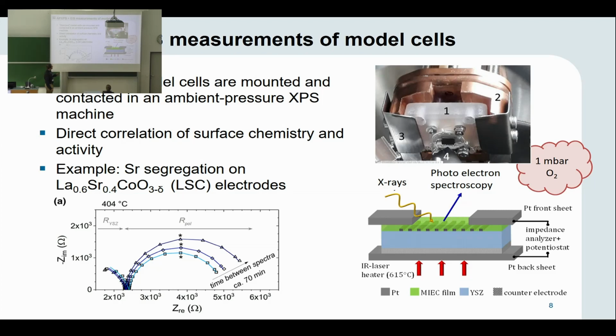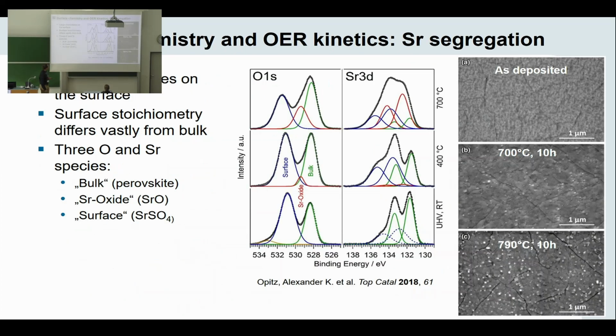And here, this is the nozzle of the analyzer, which is brought very close to the sample so that the photoelectron path in the gas phase is short, and we can measure in 1 or 2 millibars of atmosphere and at the same time heat the sample and electrically polarize and characterize it. And as a first example, I want to show you some results on the strontium segregation on lanthanum strontium cobaltite electrodes, which is a known degradation source.